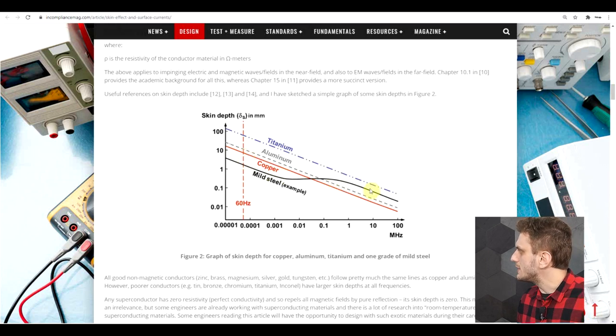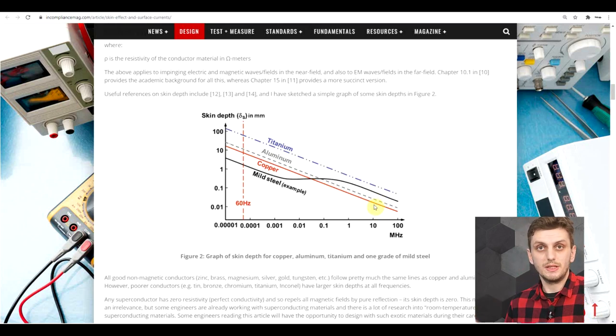At high frequencies things change a bit. The main reason for this is that although steel has permeability, it will go away at high frequencies. The permeability is not constant, it's frequency dependent, and it drops with increasing frequency. At very high frequencies, if you no longer have permeability, then the best material will be the most conductive material.